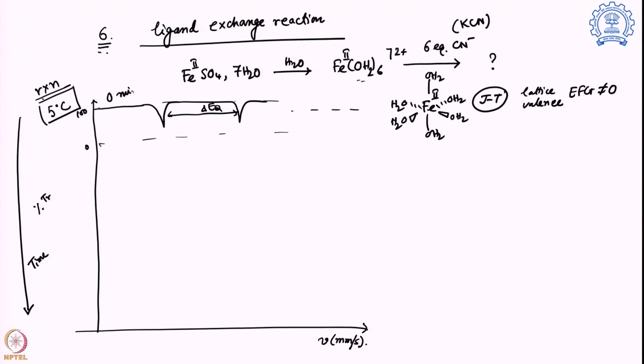This is happening at 0 minute, that means before we even add any cyanide to that, only the iron sulfate is solubilized in water and it goes to its expected hexahydrated form, showing some Jahn-Teller distortion. The next thing we started seeing after almost 3 hours is that the original peaks are present over there. But additionally, we started getting another signal very close to it, like that. So, now you have 2 doublets, one doublet in the original position and another doublet coming over here. This is what's happening at 160 minutes, almost 2 hours 40 minutes later.